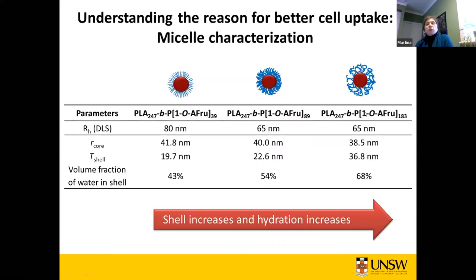So what we needed to do is analyze our nanoparticles a little bit more. And we did that with the help of ANSTO and some scattering techniques. And what we found here is that we got some information about the core and the shell size. But what was really more important is that we got some information about the hydration of the shell here. So we have here a water-soluble shell. And the longer these polymers are, the more water is inside.